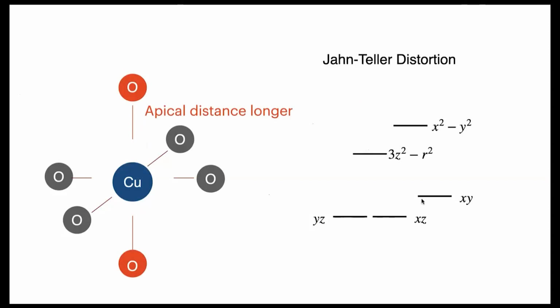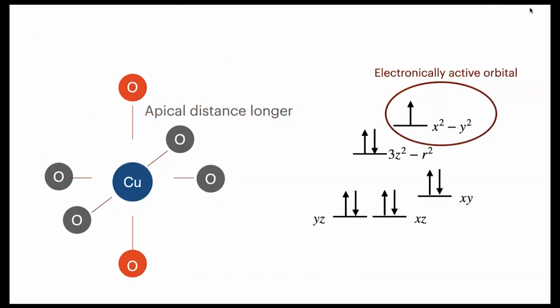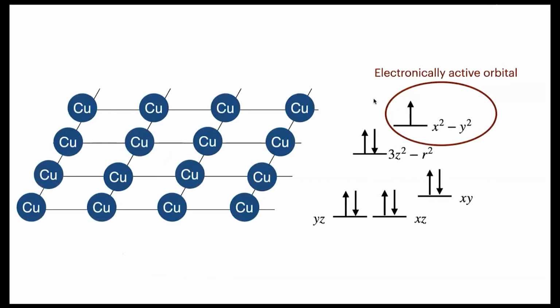The c over a coupled to this orbital order, right? But so you have 9 electrons in the d bands in this material, because you may have some rare earths here and so on, right? This isn't the whole picture. So then what you end up with is one electronically active orbital and everything else is filled. So many models for high Tc superconductors really start from this, right?